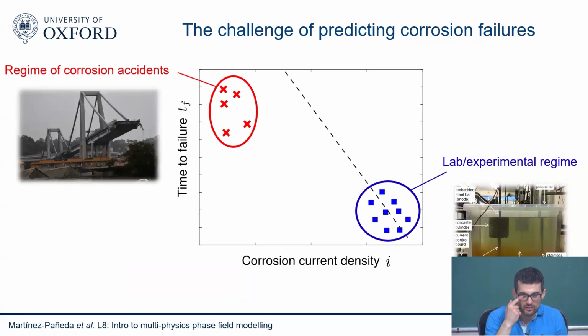And one of the challenges is that we need to extrapolate from the data. So what you see here in the sketch is the time to failure, and here is some sort of measure of the intensity of corrosion. It could be corrosion current density. And often things can fail over decades, as happened with this bridge in Italy. But in our lab, we cannot do experiments over decades. That's far more than what a PhD student is willing to stay for. So then we need to do accelerated tests.